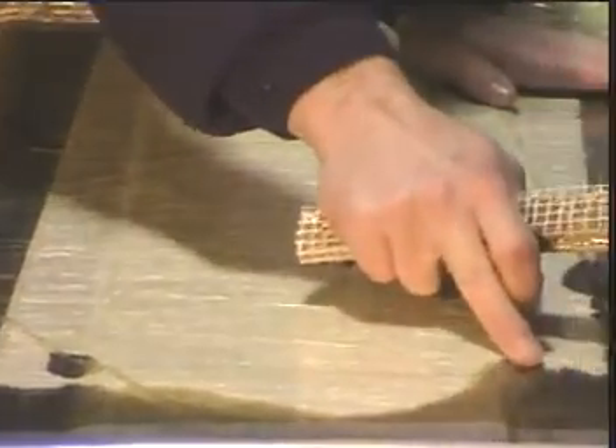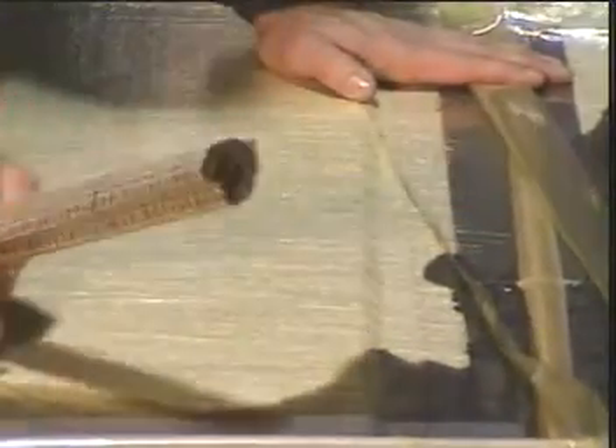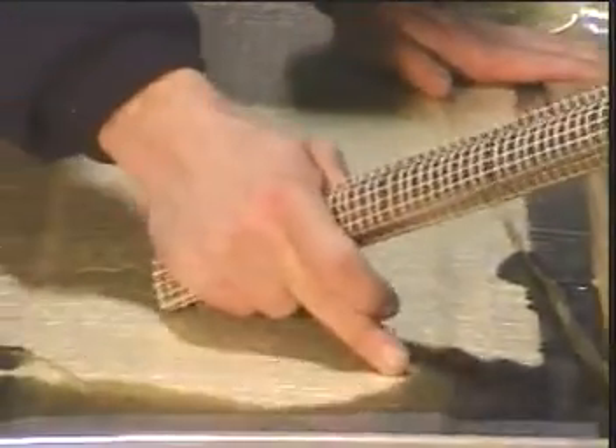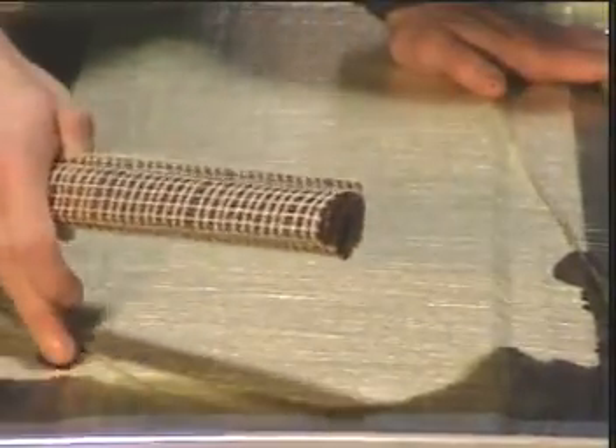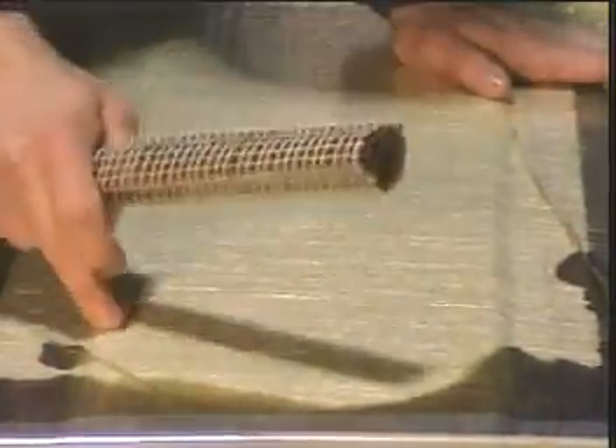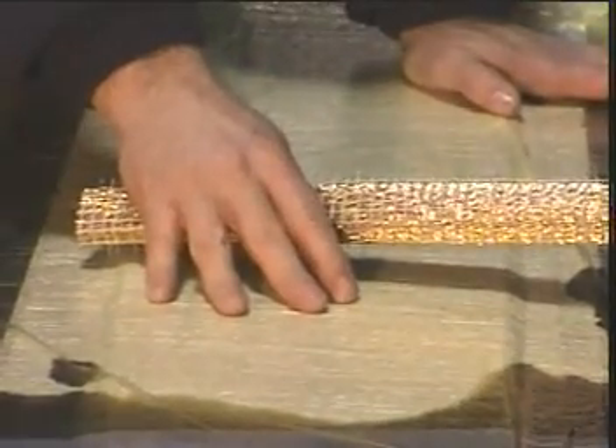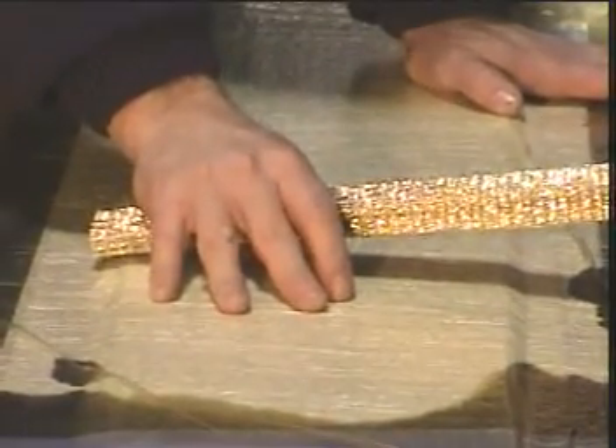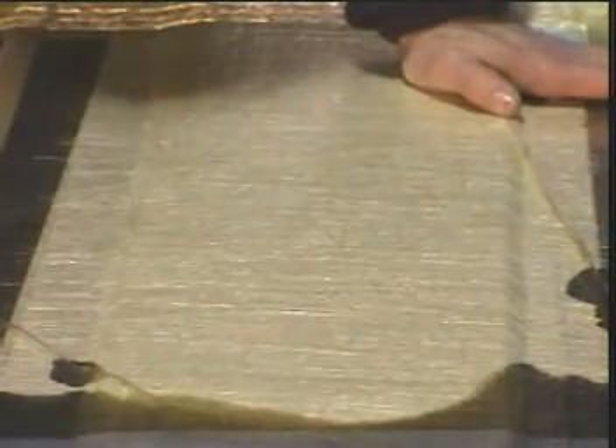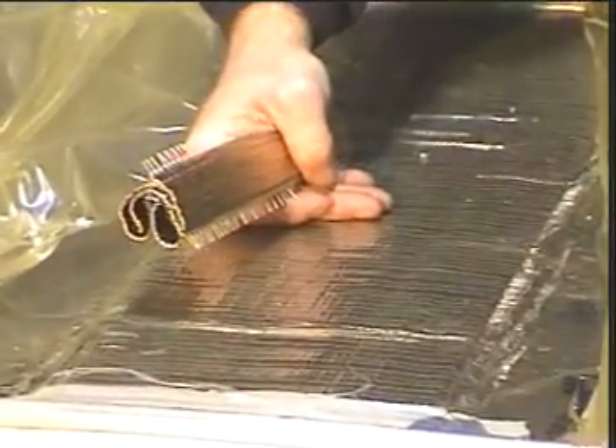2.5 inches. You can see just on the sides of the laminate where we may have a little bit less pressure in the bag, we're beginning to move up the sides of the panel. So we're beginning to form an island. Okay, if this wrinkle were to come up and come back around, we could actually island that part off. Huge quality problem. And one of the issues is in a wind blade, that could be an awfully expensive quality problem. The carbon panel, actually much to our surprise, this is a good thing.